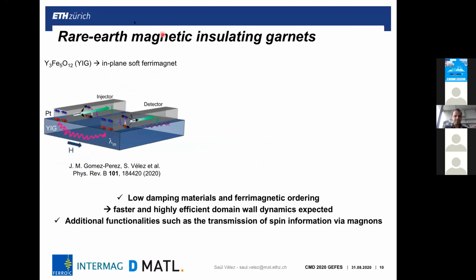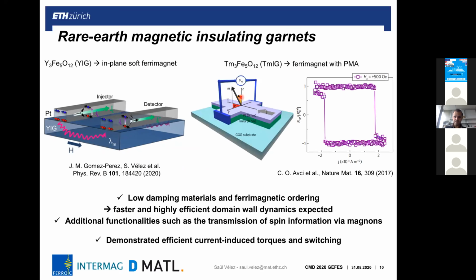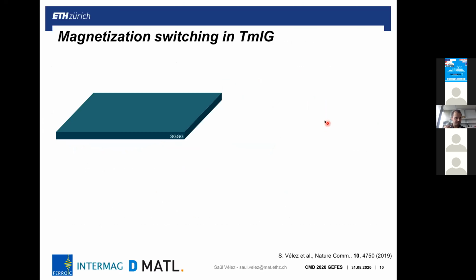So we moved to the use of rare earth magnetic insulating garnets, because these materials exhibit low damping and also have ferrimagnetic order, which are the properties that we would like to have to drive domain walls at very high speeds, but also bring additional functionalities. I'll show you that you can also excite magnon currents in the device. And it was also shown that you can drive large torques in the magnetic insulator and switch the magnetization. So now the question is whether we can stabilize homochiral domain walls in the magnetic insulator as well, and if we can drive them by spin currents. And the answer is yes, and that's what I'm going to show you.